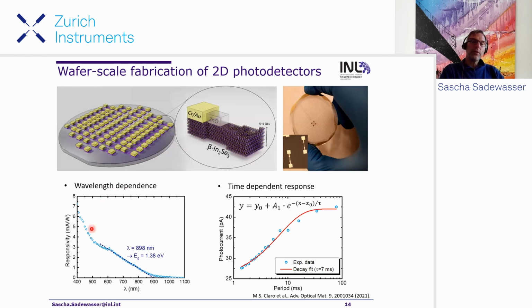So these devices have a wavelength response with a sensitivity limit, let's say, of about 900 nanometers, corresponding to 1.4 electron volts, roughly. And we also check the time dependence response. So you just use a chopper in your illumination, and you measure the photocurrent as a function of the chopper period. And then you fit this and you get a decay time here of 7 milliseconds. So one of the questions when you look at these devices is, when you shine light, what can happen is you generate charges that can get trapped in the interface defects that you obviously might have at these interfaces in your device, on the substrate, but also on the other additional layers.